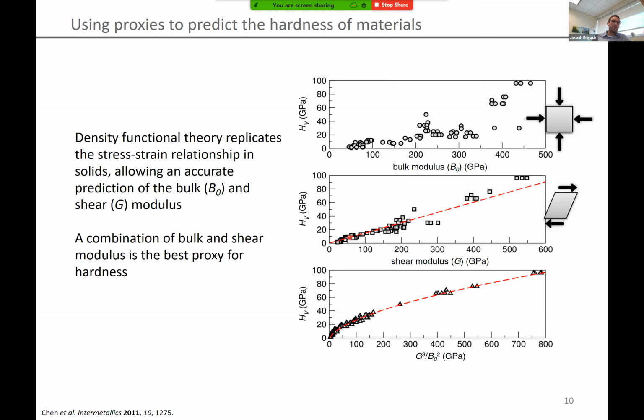This work has shown, though, that the best relationship is achieved when you plot a material's G cubed over B squared. So G divided by B is better known as Pugh's ratio, and this is like a shear modulus weighted Pugh's ratio. You can see that plotting G cubed over B squared, you get a really nice relationship over all of the hardnesses probed.